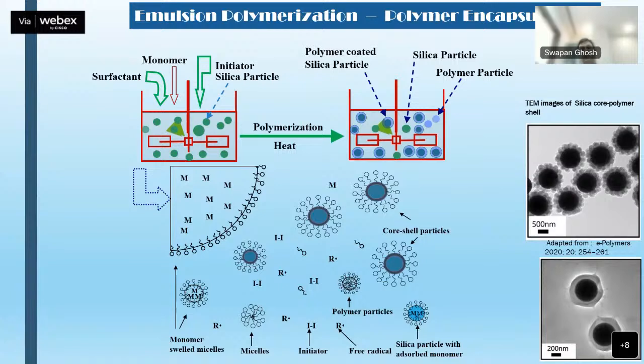And when people are using mini emulsion or other dispersion polymerization, they can actually even reach a level of, I should say, 98%, 99% encapsulation efficiency. And there are many strategies; one of them is initiator, another could be surfactant, another means all the species. What we have to do is play with the mechanism in a way that the system is not allowing the polymer particles to form. Rather, everybody is interested in the monomer which is sitting on the inorganic particle, the silicon oxide particle, and reacting there.